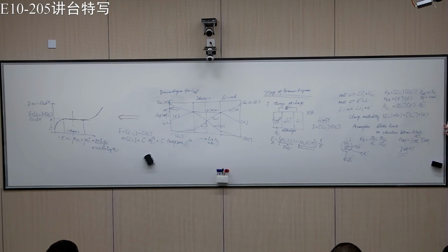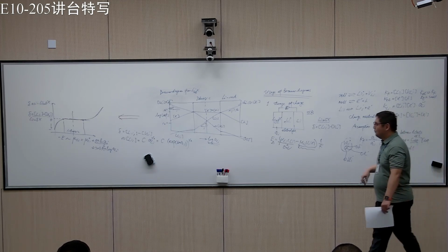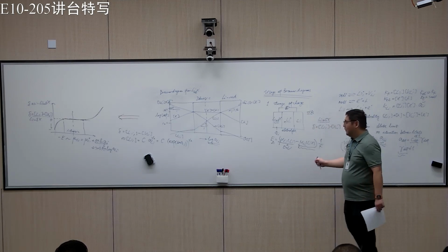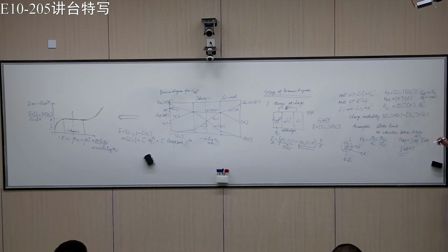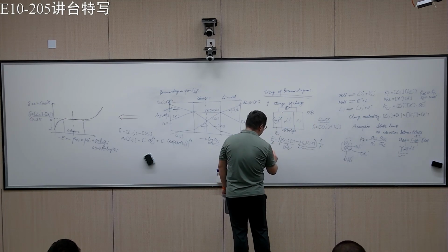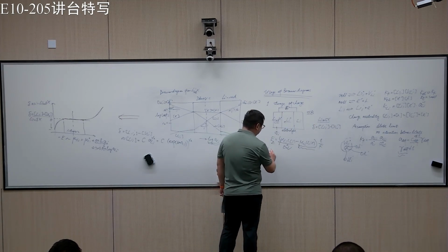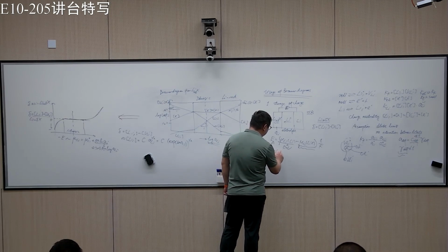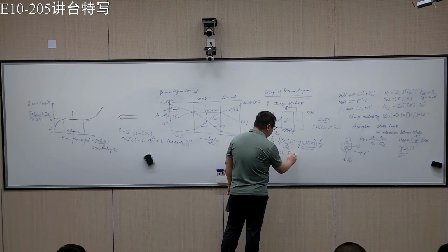Okay, so when you screw up every equation you write here, it means you cannot use the Brouwer diagram anymore. So Brouwer diagram only applies when you have a dilute system. So for oxides, in most cases, the concentration of defects is small. However, we know that for this lithium containing compound, for example, if you have lithium cobalt oxide, the delta can be as large as 0.5.